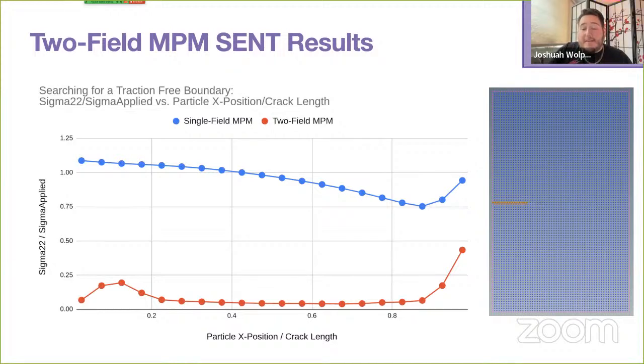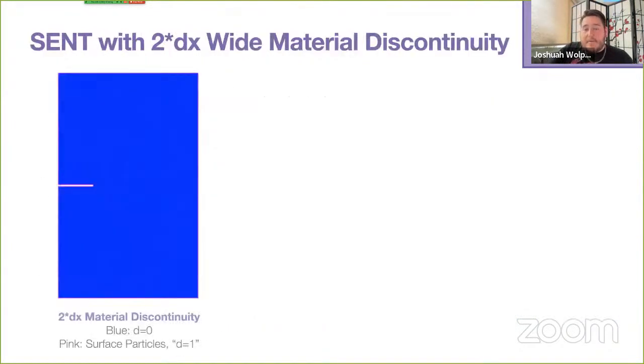However, we did find that we can improve the performance of this two-field approach by being more mindful about mesh resolution. So in this experiment, we enriched the resolution at the crack by explicitly putting a 2dx wide material discontinuity into the specimen. So now we have 2 grid cells worth of particles removed from the specimen where the crack is. And as you can see on the left, the particles at the crack surface are then detected as pink surface particles by two-field MPM and can then be treated as free surfaces in contact.